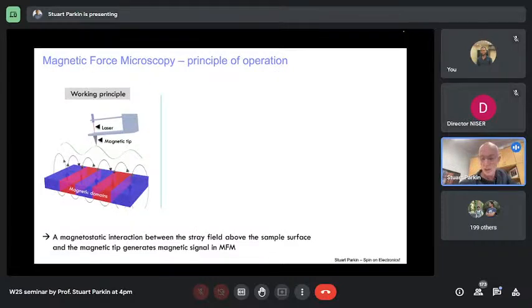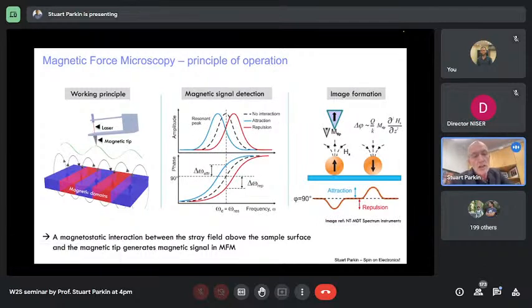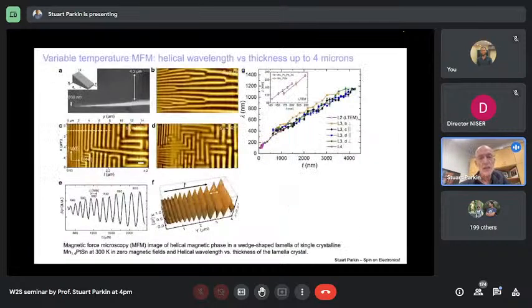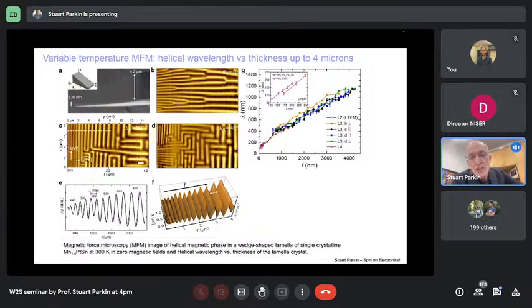And I just wanted to point out that we could also use magnetic force microscopy to detect these objects. This is shown here on the left side. You see these magnetic domains. We have a magnetic tip, and we detect the bending of that tip using a laser, and the stray fields from these domains cause the bending of the tip, and that's what we detect. I don't want to discuss this in detail, but this enabled us, for example, to see in the same material where we saw these anti-skyrmions, these spiral phases, helical phases, depending upon the temperature and the field.